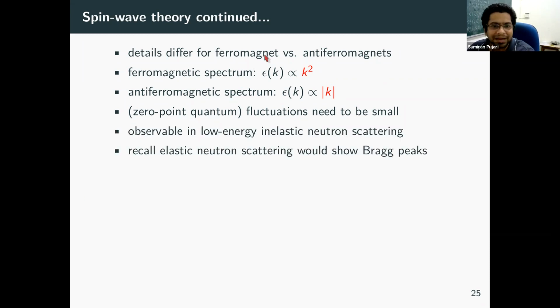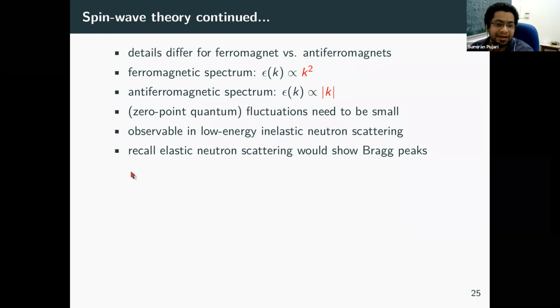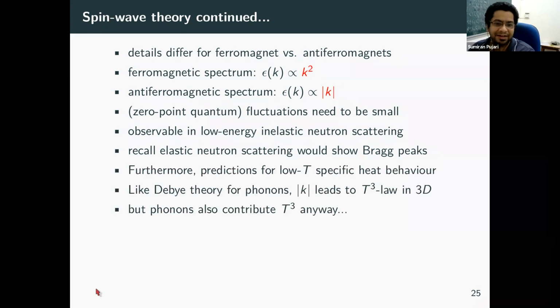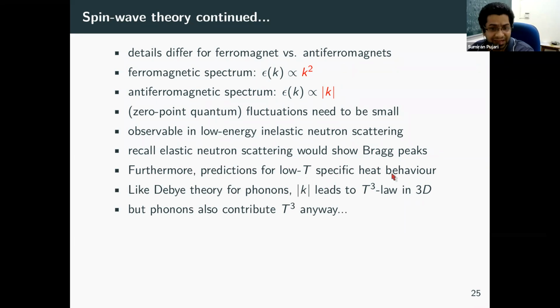The point is, this spectrum can be observable in low energy inelastic neutron scattering, and here we can recall that elastic neutron scattering would have already shown us the Bragg peaks, around which is the direct evidence of the ordering, as we discussed, Bragg's law, etc. The inelastic neutron scattering around the Bragg peaks, if it shows this kind of k square or mod k behavior, that is further evidence for the spin wave theory. You can do more work, and once you have the low energy spectrum, you can even calculate the low temperature specific heat behavior.